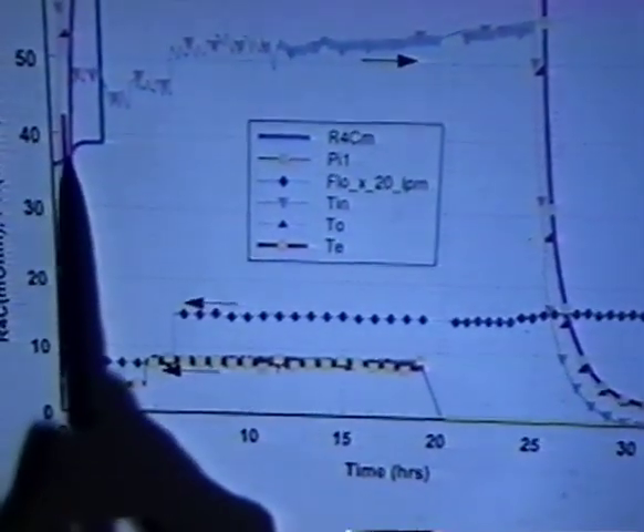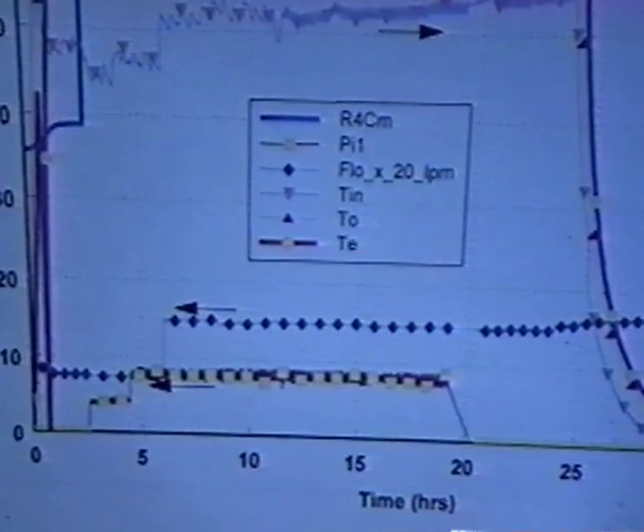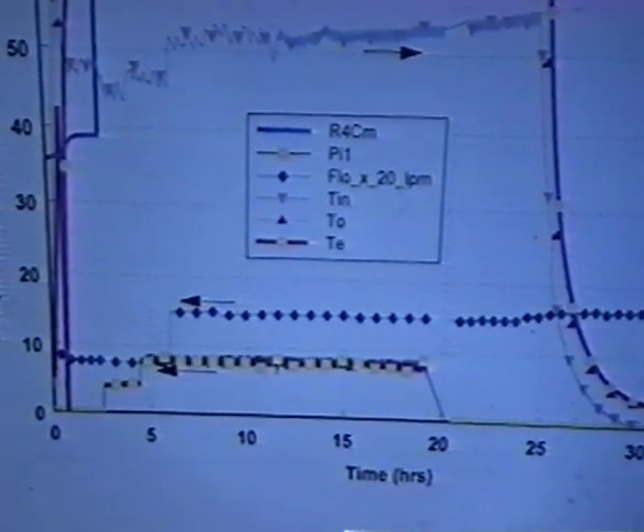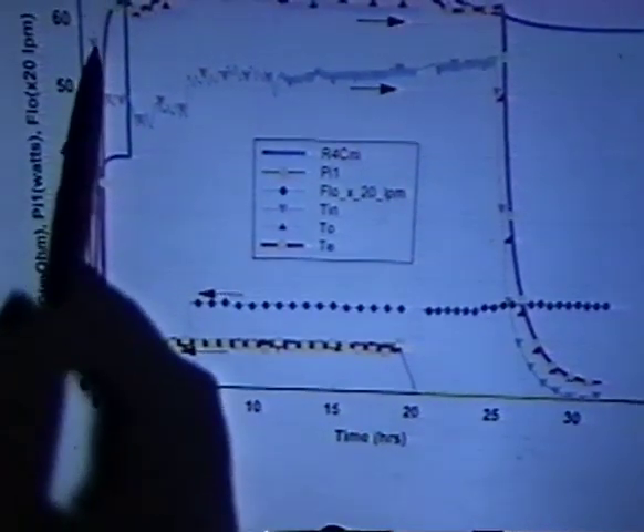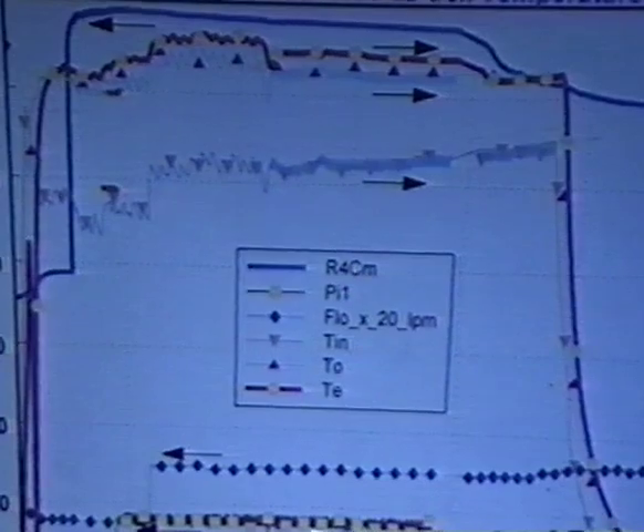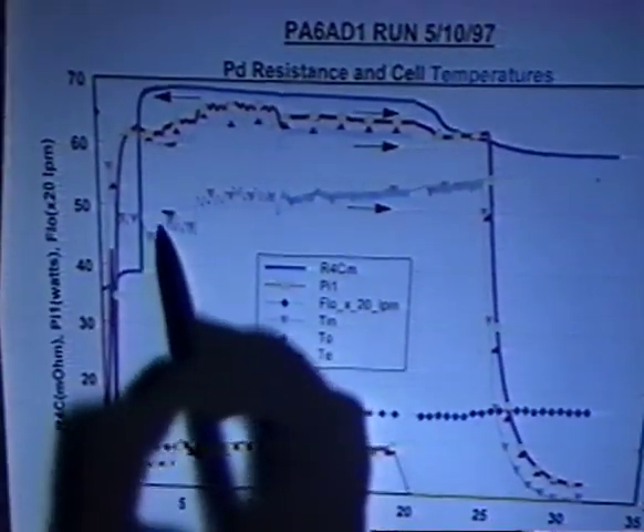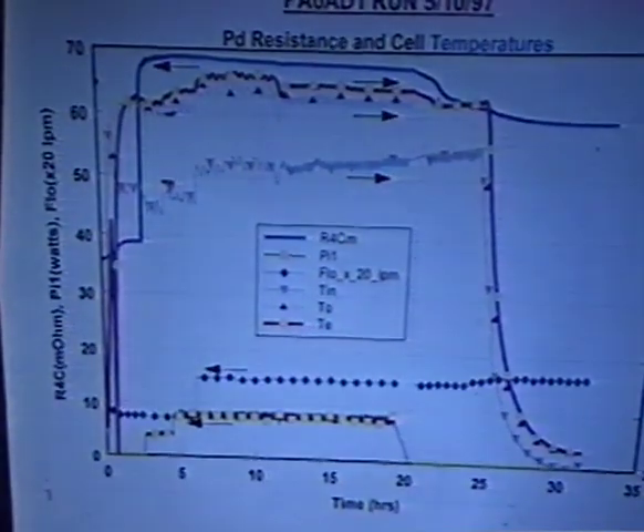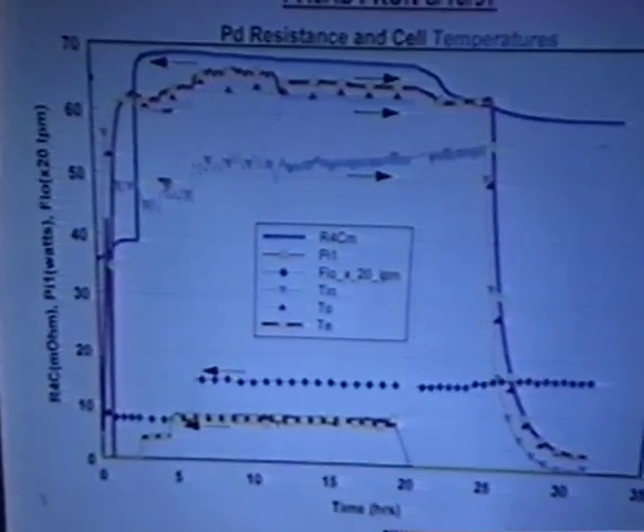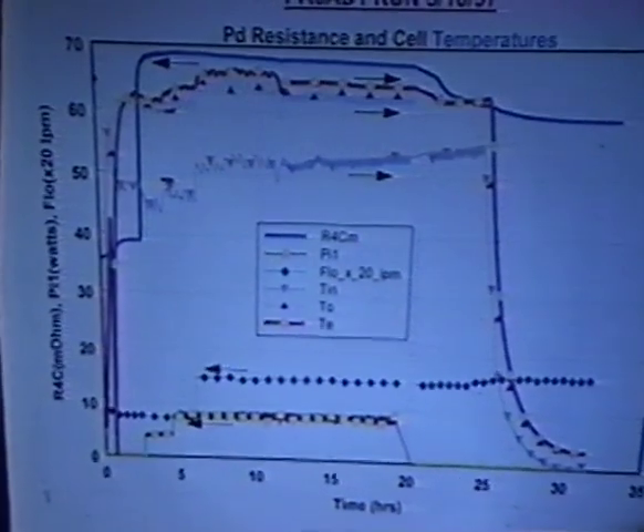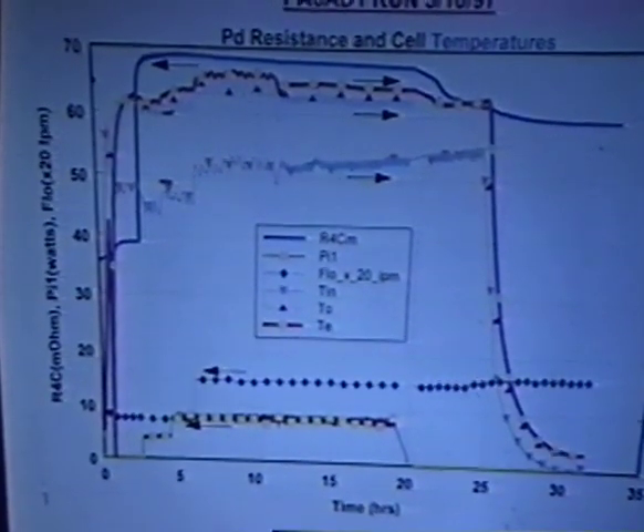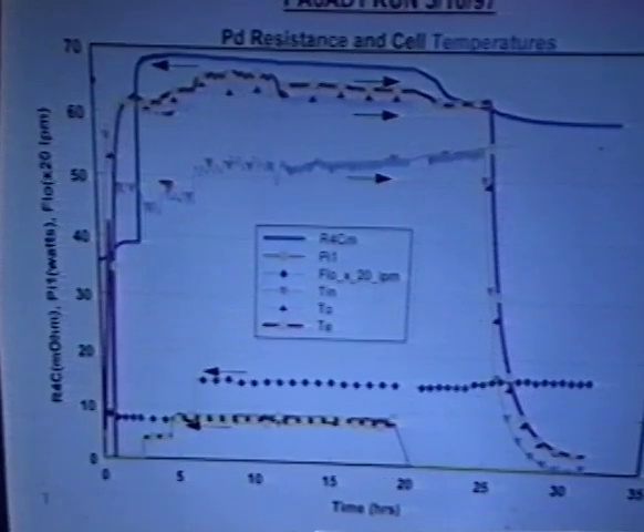And what you'll see right here, when things begin to start, this is where I poured the cell solution into an already hot beaker. The beaker was already up to near set point, poured cold solution into it, and immediately at the very top, you can see this separation between here and here. The cell temperature on the outlet, rather on the inlet, dropped. These things separated, indicating a lot of power. In fact, these temperature differences are about 14 to 15 degrees centigrade. And there's just no way to argue that was not real, even with this system with two thermocouples. So a lot of power, and again, the visual observation was an incredibly active cell, lots of carbonate being formed, and also reabsorbed somehow or redissolving back into the solution.